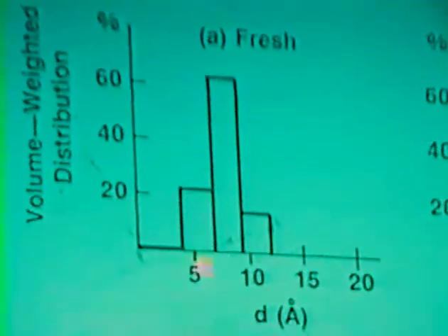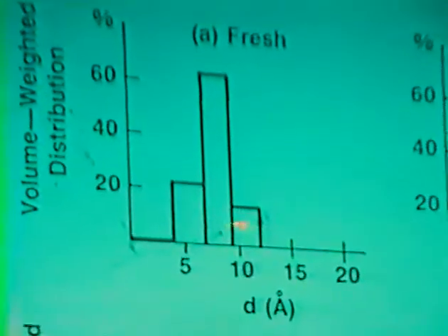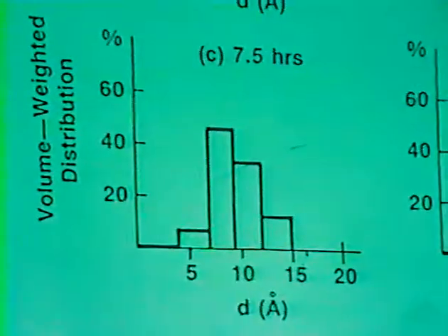And that's indicated here, where the particle sizes are compared. The particles that are less than about 10 angstroms are the ones that are inside the pores of the L zeolite. It has parallel channels with openings of about 12.6 angstroms if you ignore the cations. If you put the cations in there, it's just about 10 angstroms.